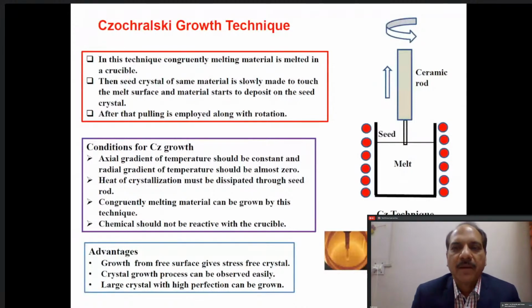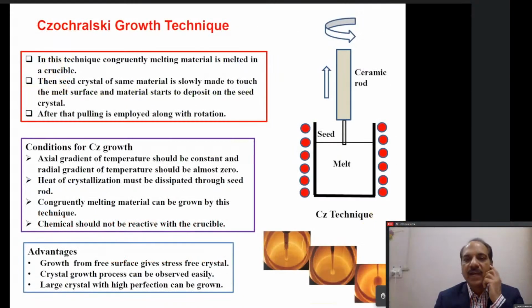And the first step in growing a crystal by the Czochralski technique is you have to prepare the starting material. That starting material is what we call the charge. That starting material is prepared mainly by the solid state reaction method. So in solid state reaction, you have to mix the two or three or whatever number of compounds are there, as per the stoichiometric chemical reaction, and mix them in a mortar and pestle, then keep it in a furnace, following a particular program so that the material is heated up, and during heating the materials will react with each other. Finally you might have to follow this heating cycle a few times, and also crush your material so that the reaction is completed and you get the final starting charge.